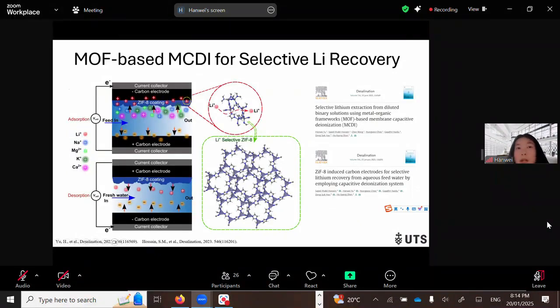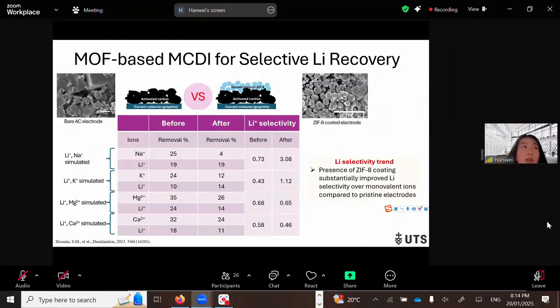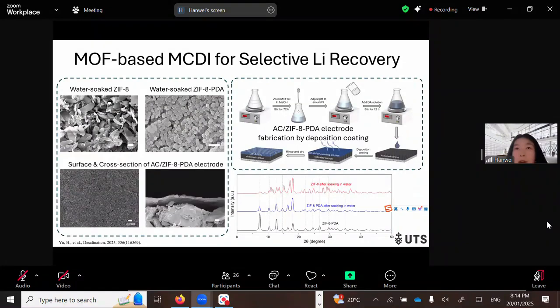We used the in situ growth method to simply grow ZIF-8 on the activated carbon electrode. The result shows that the presence of the ZIF-8 coating substantially improved the lithium selectivity over monovalent ions compared to the original electrode. But it has a problem, which is the poor hydrostability. To solve this problem, we further used polydopamine to modify ZIF-8 and coated ZIF-8 polydopamine on the activated carbon electrode through the deposition coating method. The SEM and characterization results both confirm the greater improvement of the water stability.